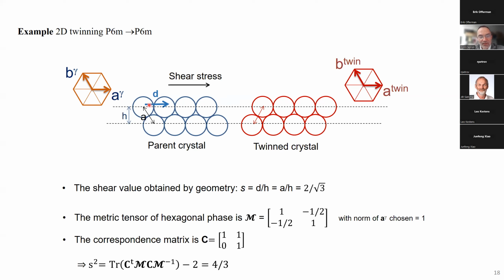If I want to calculate the shear amplitude of the twinning, it's this distance here, d, divided by the interplanar distance here, h. And if I do that geometrically, it's very easy. It's 2 divided by the square root of 3. Okay. Well, in this simple case, geometry gives you the answer. But I can tell you by experience that if you want to do that with 3D real crystals, geometry does not work anymore, or it does not help you so much. But on the opposite, if you apply the Bevis and Crocker formula, it gives you immediately the result.